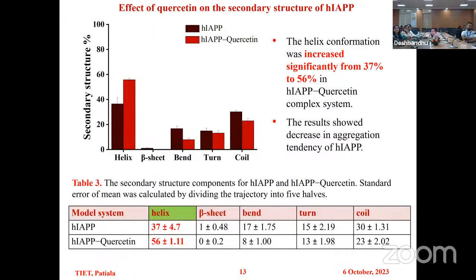This is the data that we got, that helix was around 37% for HIAPP, and in presence of quercetin, it was significantly increased to 56%. And also the beta sheet structure was reduced from 1% to 0%. So this shows the decreased aggregation tendency of HIAPP.